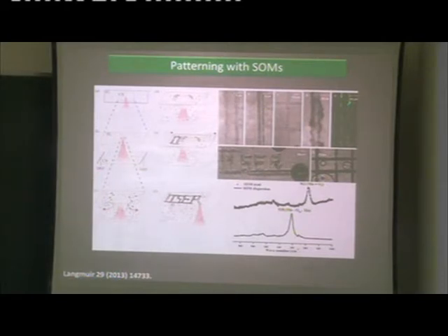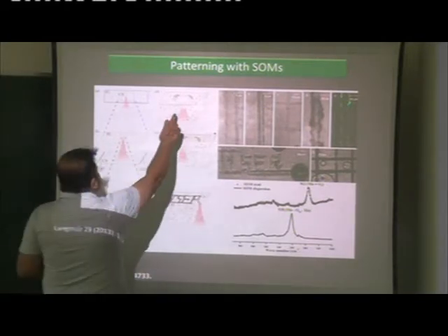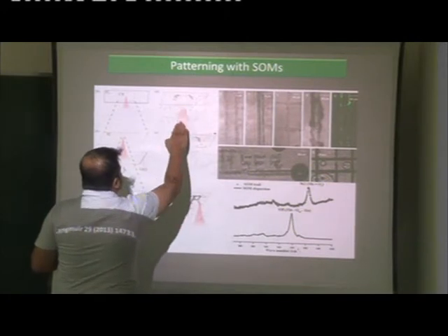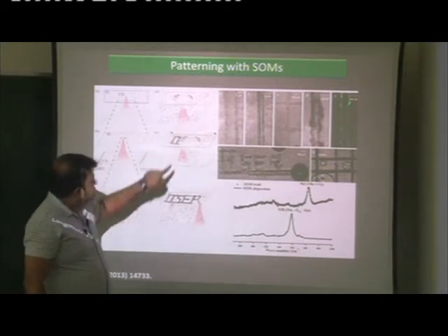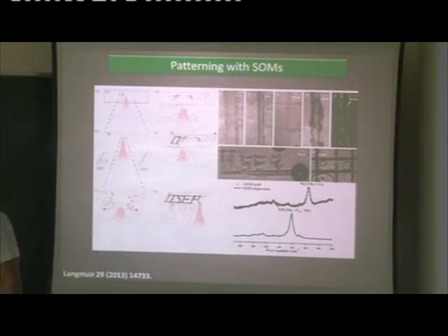And then if we move the laser, the bubble moves with the laser. As we move the bubble with the laser, we are able to see phase transitions and thereby formation of controlled patterns because of the deposition of the polyoxometalates. This is how we were able to write the patterns, right? We were able to put carbon nanotubes, perylene tetracarboxylic acid and so on, and we were able to write patterns as we would like to have them.